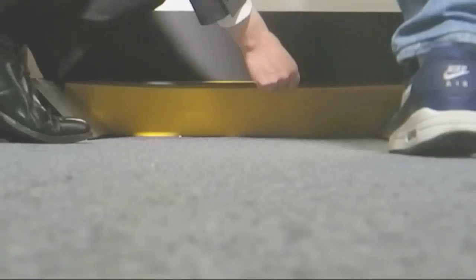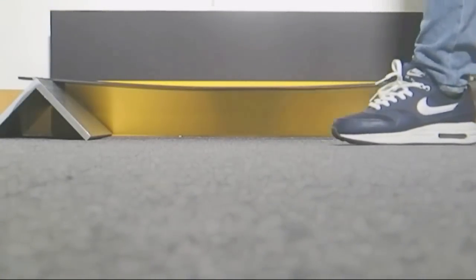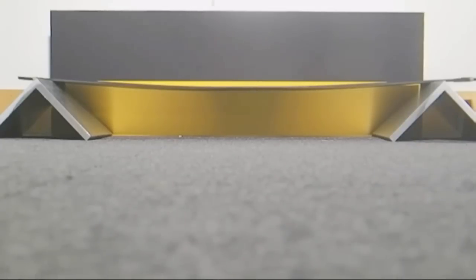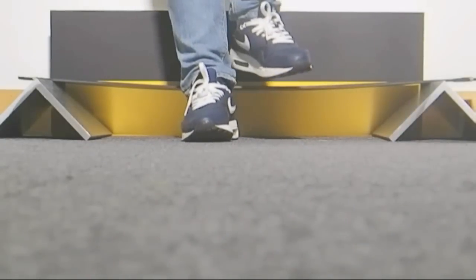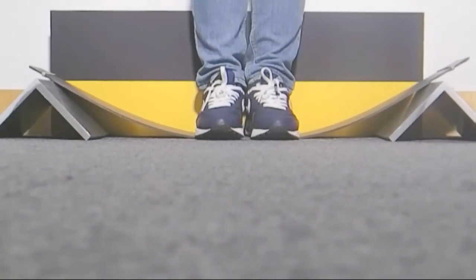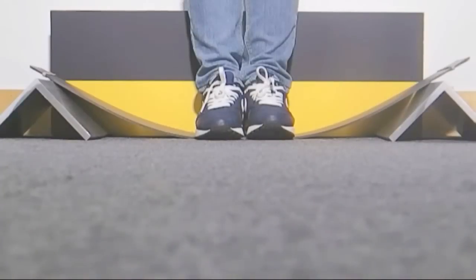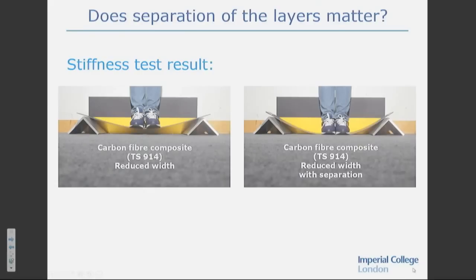So, there we go. And just before you stand on it, you will notice something already, and you'll have an inkling about what's going to happen, because you'll notice it's sagging significantly under its own self-weight. Okay, go on, stand on this. That was the one, careful, that was the one reduced width one without the separation, so it was the solid laminate. This one, well, look what's happened. When we have separation, Jingjing's actually standing on the floor here. The composite isn't doing anything. In fact, so there's a picture of it. In fact, the stiffness is less than 2% of the original plate. Okay? So we've lost a huge amount of stiffness. Jingjing, you can sit down. Thank you.